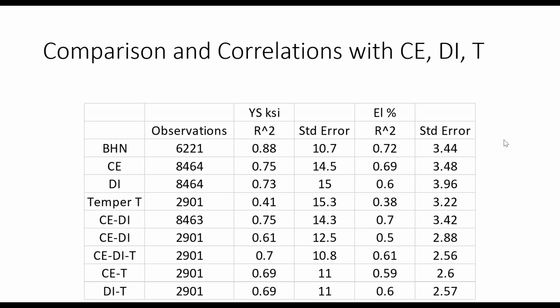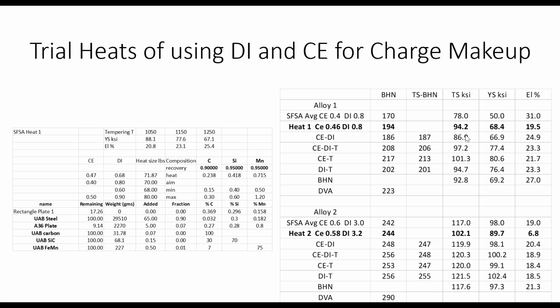So this is the kind of correlation that I'm planning to do, but this is how I put together the trial heats. I take this correlation matrix and calculate the chemistry, and then I plug the chemistry in here. This is a spreadsheet that I'm developing where I can put my charged materials here, the composition of the charged materials here, calculate what the estimated heat composition is, get the carbon equivalent and DI, and that allows me, for different tempering temperatures, to calculate what I think the properties are going to be. And so I can look at different ways of predicting the properties here.